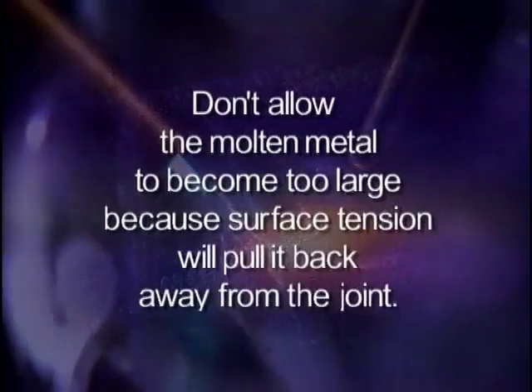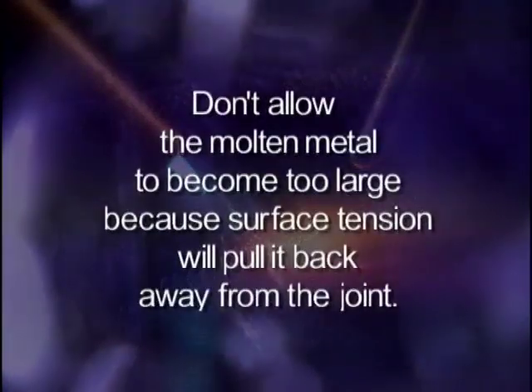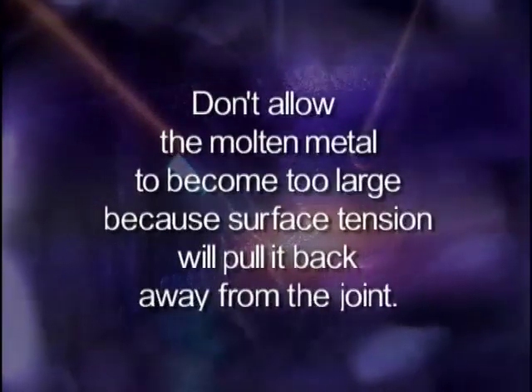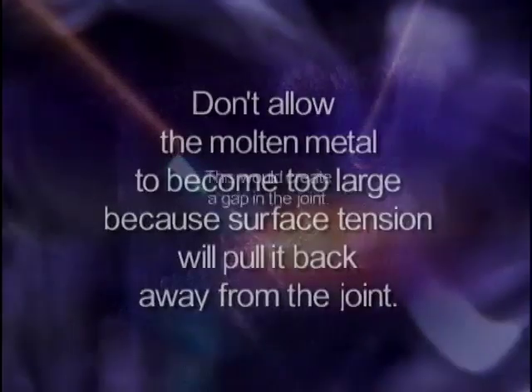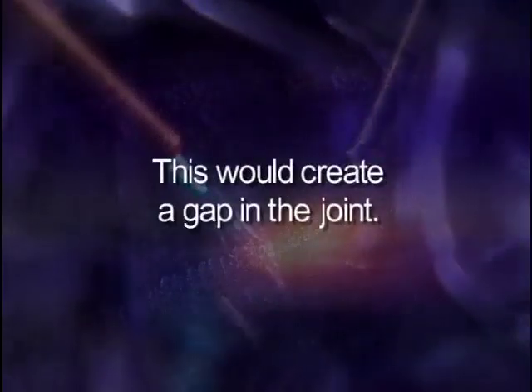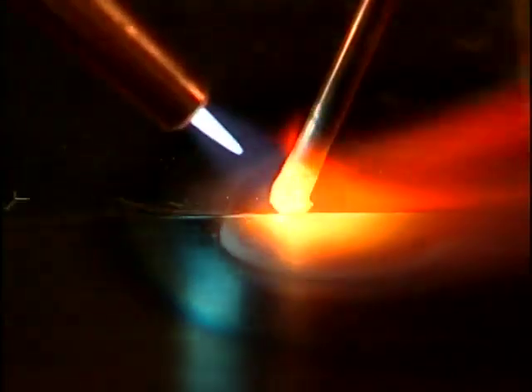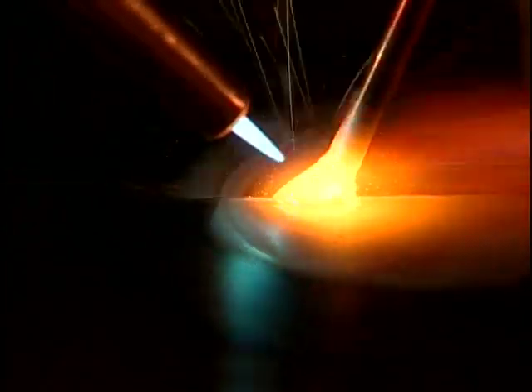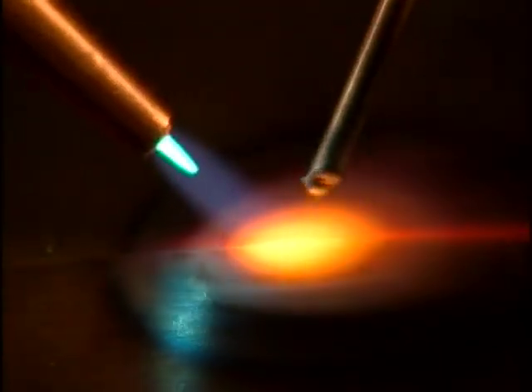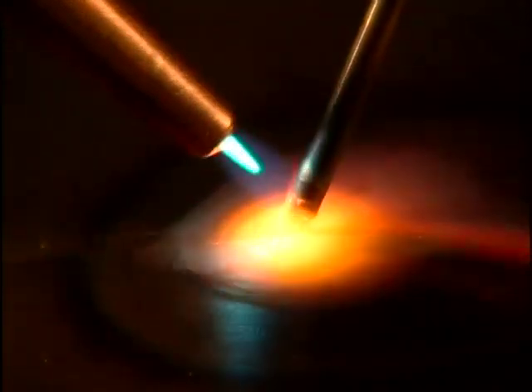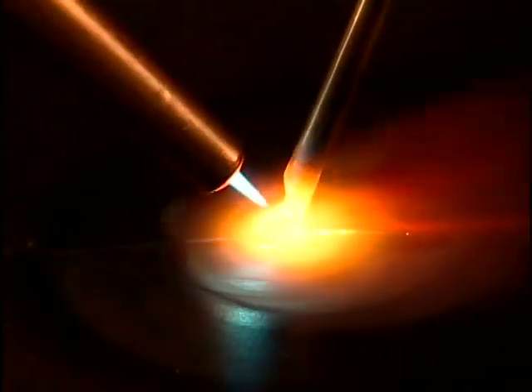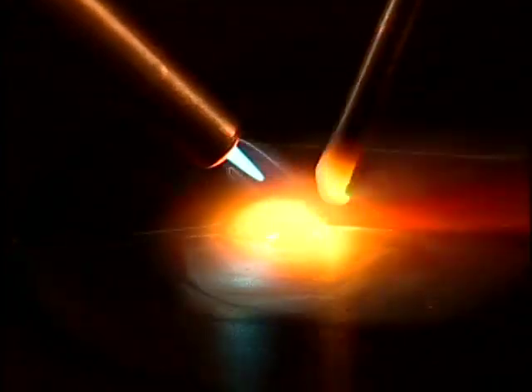Don't allow the molten metal to become too large because surface tension will pull it back away from the joint. This would create a gap in the joint. When the molten pool has been established on both plates, add a small amount of filler metal. Repeat this process on the opposite end and in the middle as required. When using thinner materials, additional tack welds will be required to prevent the joint from becoming distorted as the weld progresses.